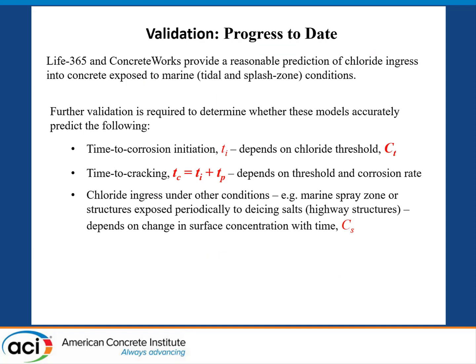Validation to date, we're reasonably confident that Life-365 can provide a good estimate of the chloride profile in both the tidal and the splash zone. We still need more work to look at time to corrosion initiation, as we need more work on the chloride threshold. And we also need more work to characterize what happens under marine spray conditions or concretes that are exposed periodically to de-icing salts like highway structures.